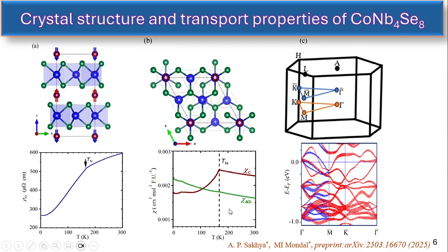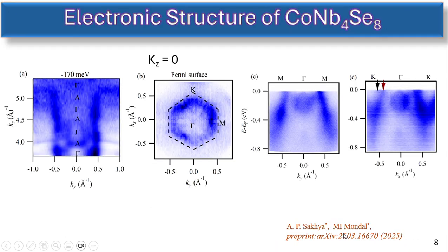At the same temperature of 267 Kelvin. So this is the spin resolved electronic structure that is predicted to host the alternating spin phenomena just below the Fermi level along the gamma M direction, but there is no spin polarization along M-K or gamma-K direction.